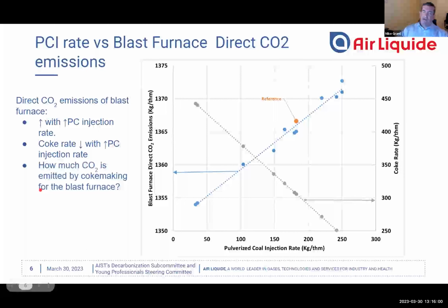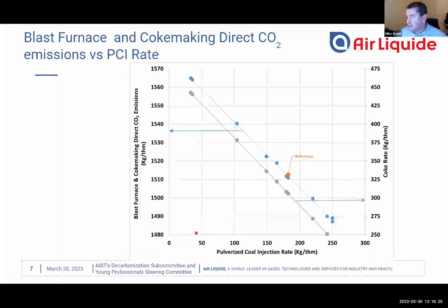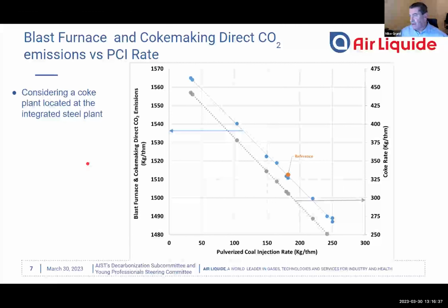But how much CO2 is emitted from the coke making process? So we can get pretty good, you'll see later on, pretty good calculations of CO2 emissions reduction in the blast furnace, in just looking at the blast furnace itself. But we have to consider also that when we are increasing our PCI, we're also decreasing our coke rate. So the graph turns into this type of graph when we include coke making on the direct CO2 emissions y-axis. And so if we consider a coke plant located at the integrated steel plant, the CO2 emissions of that coke plant are included in the overall plant emissions.